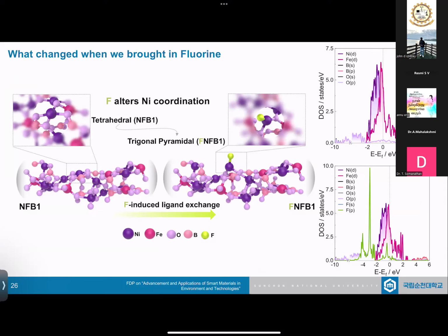So we kept on asking the questions. Still, the question is how it's altered and why it's altered. As I said, the bonding nature of nickel is shown over here. This is a pure structure. This is the nickel orthoborate structure with iron being doped in a small concentration. You can see iron being present in a very small concentration compared to the nickel atoms. So what did we do? We brought in a fluorine atom, and we didn't attach it directly to the nickel, because we still have to find out, is it really attaching to the nickel?